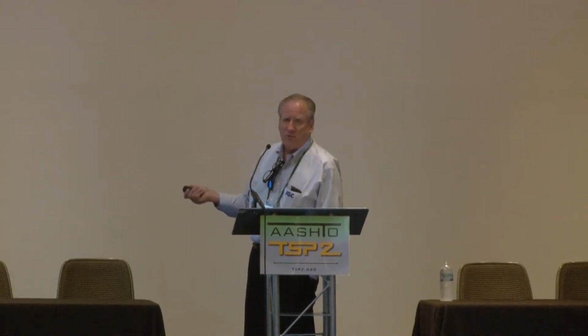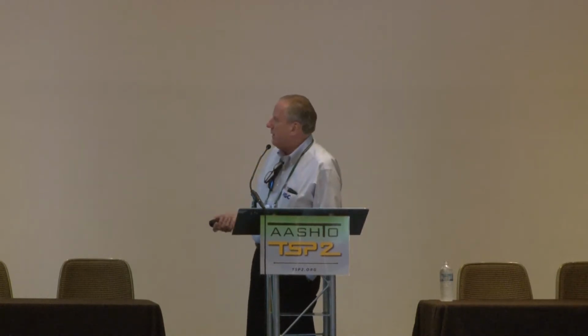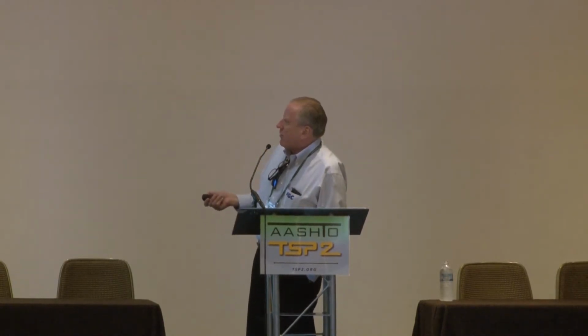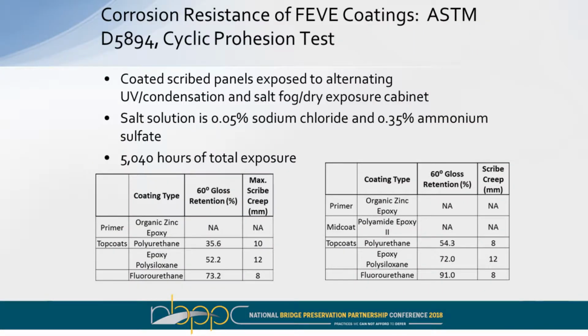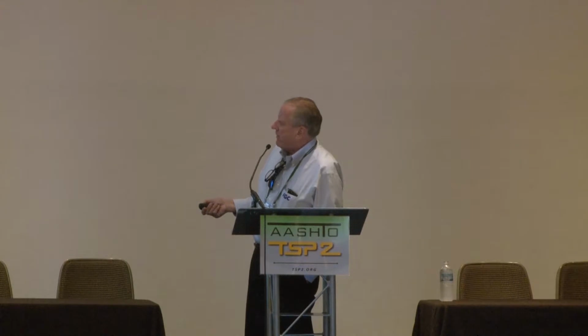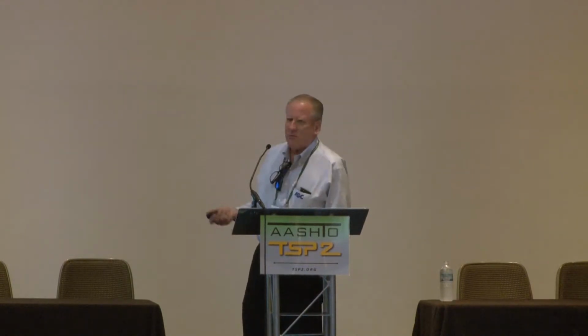These are also exposed in a weatherometer to some form of ultraviolet light. And the same thing over here. You're just looking at a different zinc-rich primer over here and a different polyamide epoxy over here. And again, you can see the difference in the gloss retention, and you can see the urethane and the fluorourethane offer about the same corrosion resistance. So a lot of the performance in this test is really driven by the primer that you pick. It's not necessarily driven by the top coat.